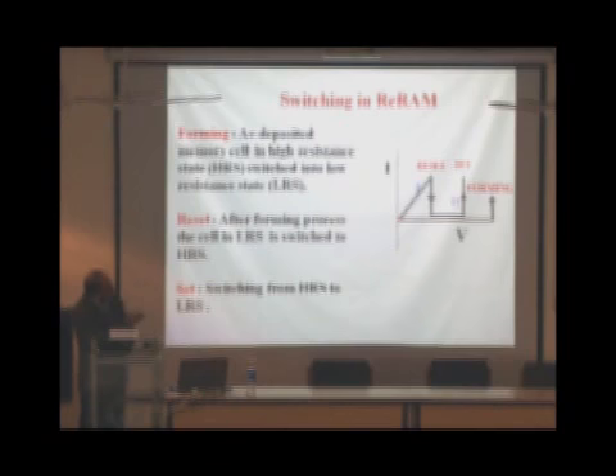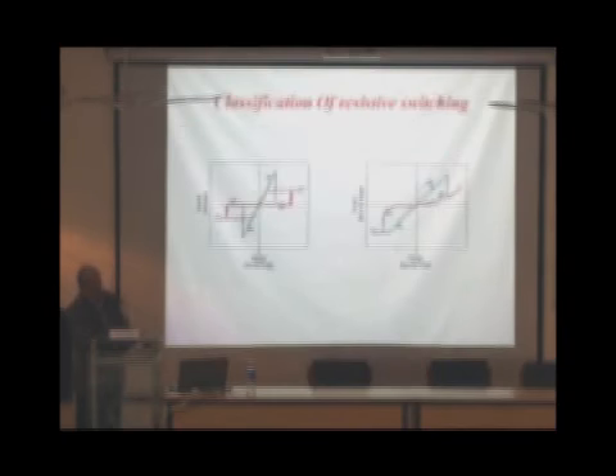So when you come back to this and you increase the voltage, the device after the electroforming step is in this mode. You call it the low resistance state, or you can call it state 1. On application of the voltage equal to this reset point voltage, the device goes from state 1 to state 0. Its resistance increases. When you apply the set voltage, the device again goes back to the low resistance state. So by applying the reset voltage and the set voltage, you can change the state of this device from low resistance state to high resistance state and back and forth. So this is a simple idea of how this kind of device can work as resistive random access memory devices. And there are two kinds of characteristics one normally gets.